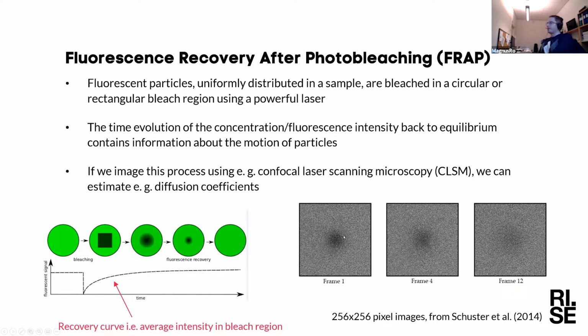So you can see some real data here. This is directly after this bleaching where we kill off fluorescence in a circle. And you see that this spot degrades and disappears with time. And eventually we don't see anything anymore. So if you plot the mean intensity of the fluorescence in the region that you bleached, you're going to see something which eventually recovers because of this diffusion, and you're going to have the same intensity again. So this type of curve is the data that we have from which we want to try to estimate the diffusion coefficient and other parameters.